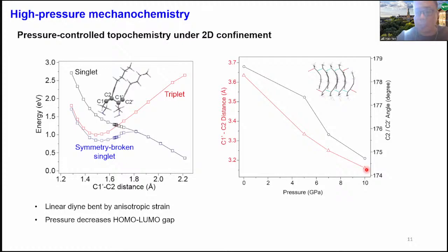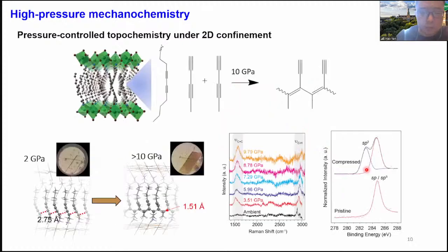And that's where the two-dimensionality of this particular system comes in. Looking at the structure, this is apparently a very mechanically anisotropic system. The in-plane compressibility, governed by the covalent and the ionic lead bromide bonds, is extremely small, so this is very stiff in-plane, but out-of-plane, there's only van der Waals interaction. So the whole crystal is much more compressible in the z direction, the out-of-plane direction, even if you're applying isotropic pressure to it.